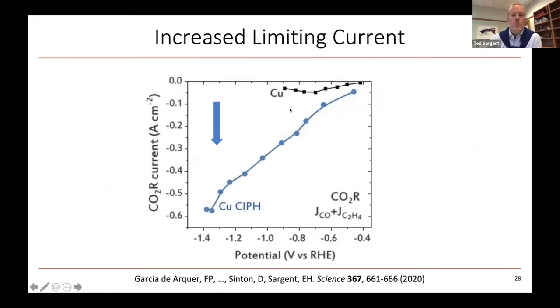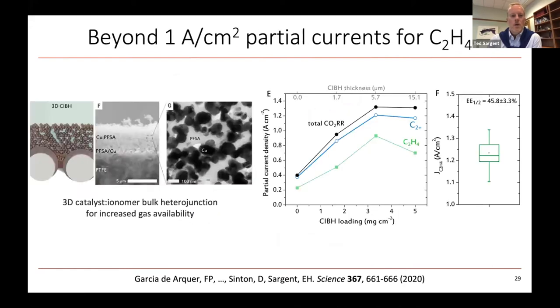And relative to a copper control that did not benefit from the CO2 transporting material, you can see here that we went from about 100 milliamps or even a little bit less, all the way up to 0.6 amps in these initial studies. And then when we really built out a three-dimensional structure,